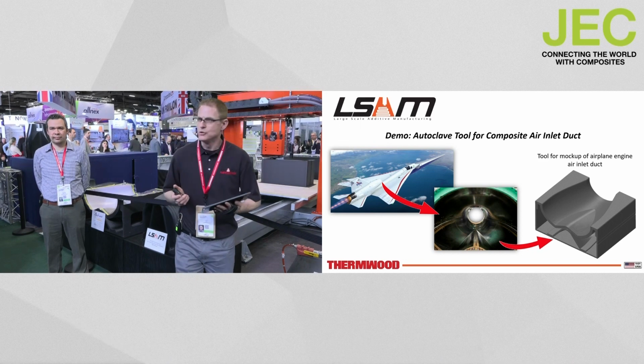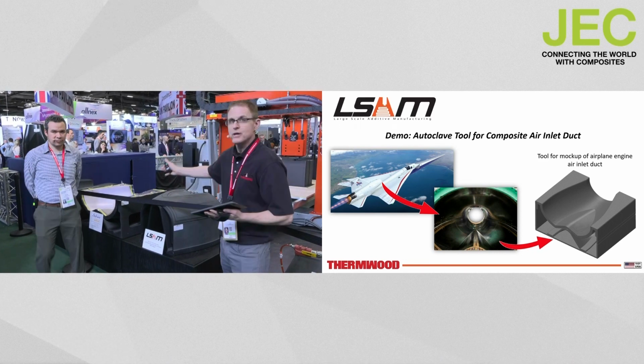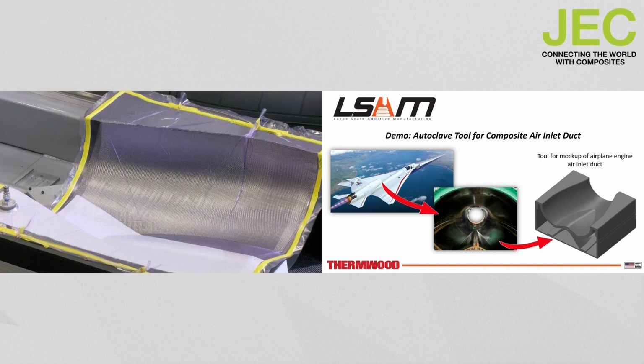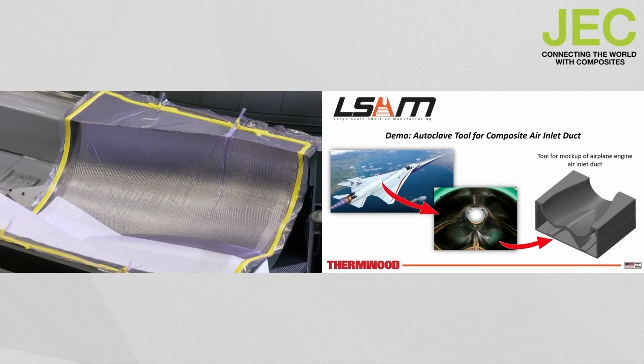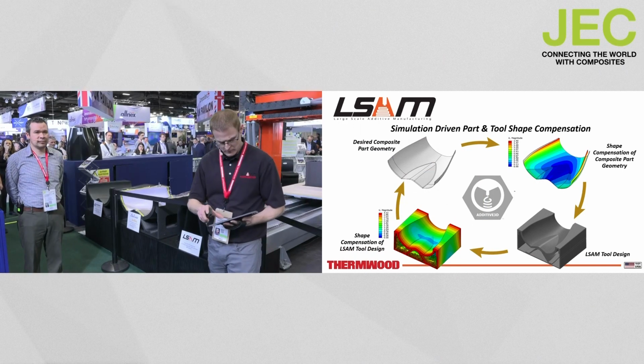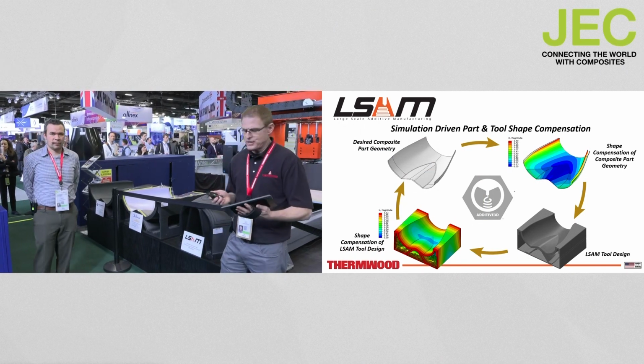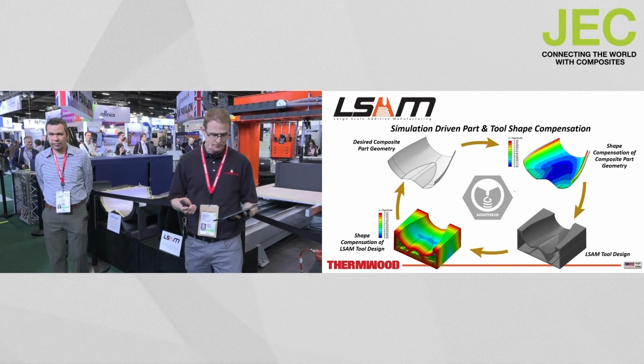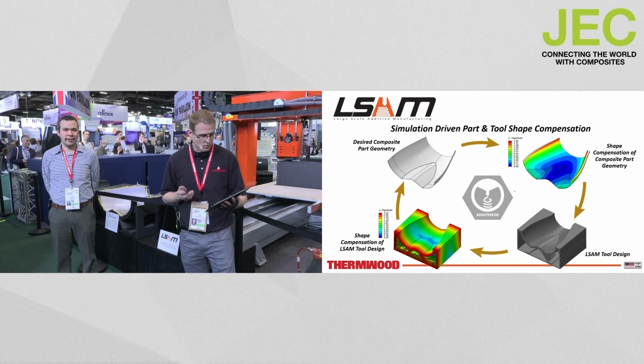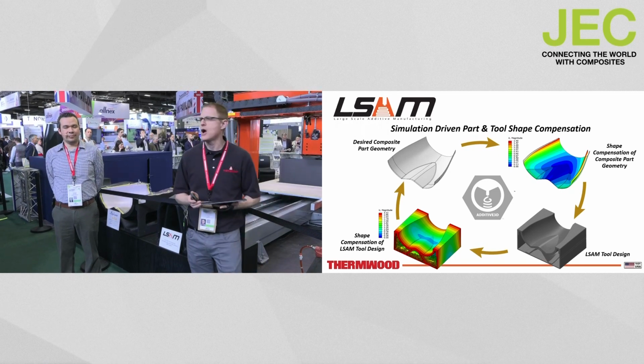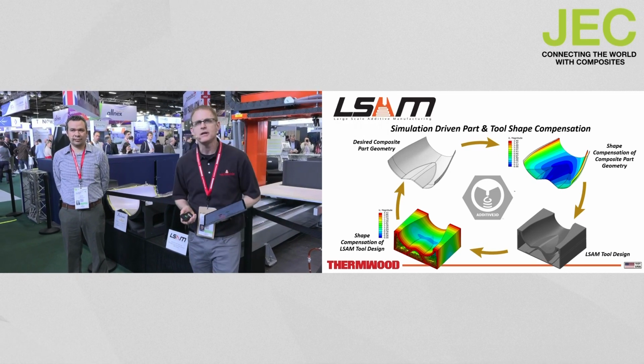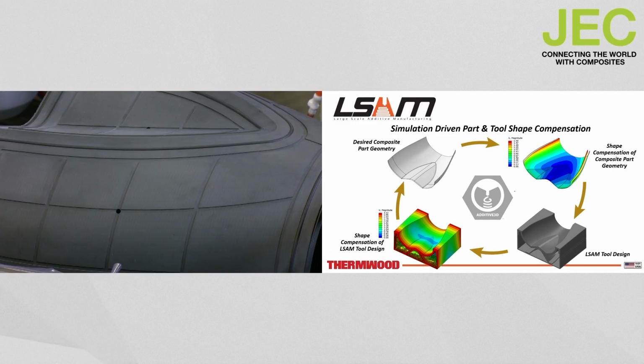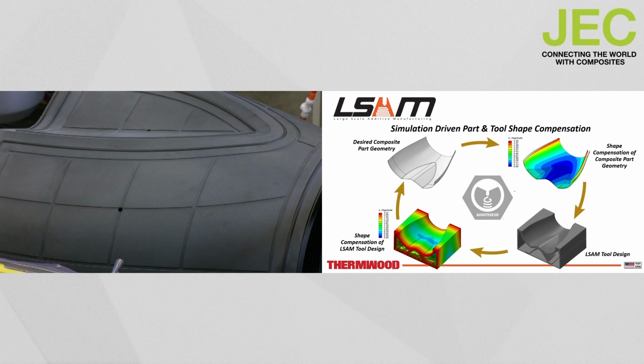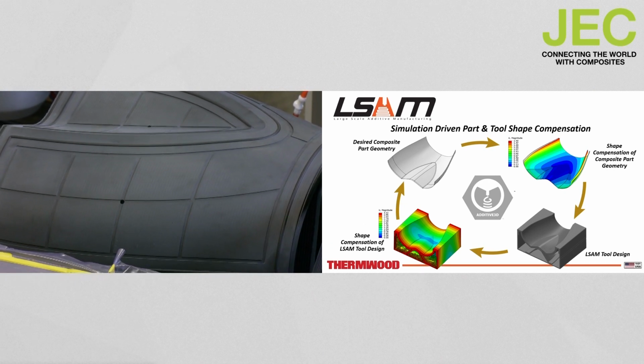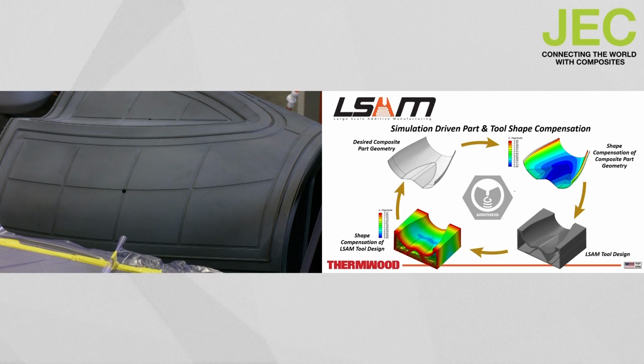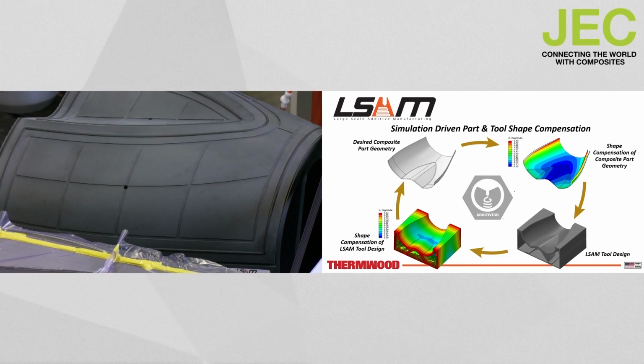In fact, the tools and parts used in this study are actually here with us today, and we're also printing another set of tools live for you as we speak. We want to explain the important steps needed to be successful with this process, from how we achieve LSAM quality prints to correctly compensating for anisotropic CTE and other shape changes that happen during the autoclave cycle. And it is also important to understand and compensate for pre-preg material springback, which occurs on the laminate layup material itself during its curing process.